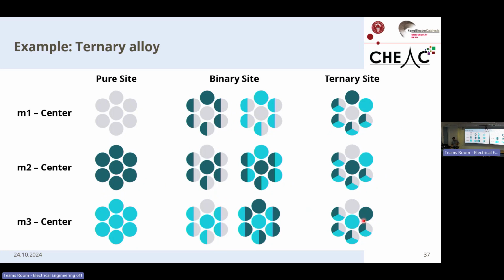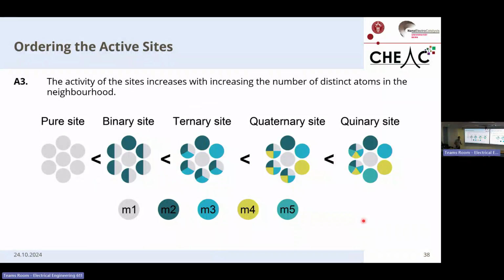So now, as we have defined the active sites and grouped them together, we cannot assign an activity to them, but we can already group them how we would see them in our activity distribution. So the more complex an active site is, the more you invest to make it, the more active it should be. Because if it doesn't make up for its activity, it's not worth going up in complexity. So the 5-element site is expected to be the most active.